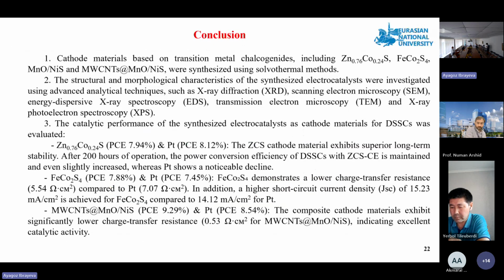Conclusion. Alternatives to traditional metal chalcogenide based cathodes: zinc cobalt sulfide, iron cobalt S4, and the composite of manganese oxide and nickel sulfide with multiwalled carbon nanotubes were successfully synthesized using solvothermal methods and characterized by XRD, SEM, TEM, EDS, and XPS.